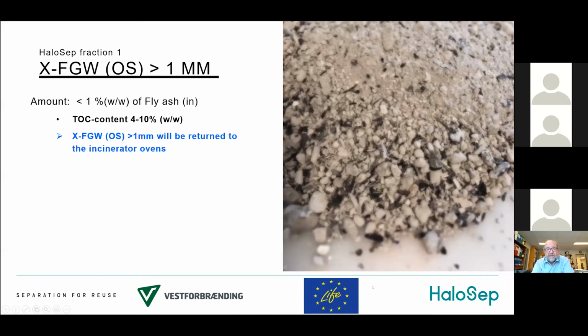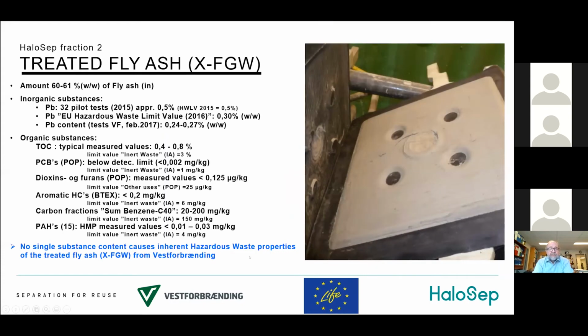It's a very small fraction, less than 1% of the incoming fly ash. However, it has a very high TOC content. You can actually see the black stuff on the picture. So this material will be returned to the incinerator ovens. Next slide, please. If we look at the treated fly ash, the amount of that will be about 60%.